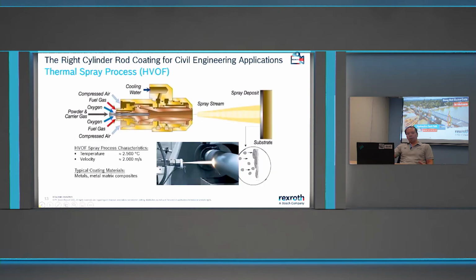So talking about the HVOF thermal spray process, it's a coating process in which the powder, usually a matrix of metal, is heated by burning gas and oxygen, and after that it is sprayed onto the substrate to build the coating. And in the HVOF spray process, you don't need a very high temperature like the plasma. The temperature is about 2500 degrees Celsius, and the velocity is high, about 2000 meters per second. The typical coating material is metal, and in that case we use mostly chromium and nickel.